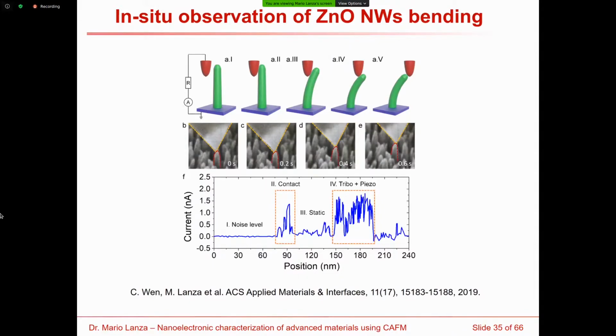And this is very useful. And in this paper, we solved one problem that was unresolved for 13 years. In 2006, Professor Zhong Lin Wang from Georgia Tech published in Science one revolutionary paper where he demonstrated that zinc oxide nanowires can produce current by piezoelectric effect. And they did one experiment with one standard conductive AFM that scans the surface of the sample. So until we did this work, it was thought that all the current produced is related to piezoelectricity. But thanks to this setup, we could demonstrate that the currents produced are not only related to piezoelectricity, but also to contact potential difference and to triboelectric effect.